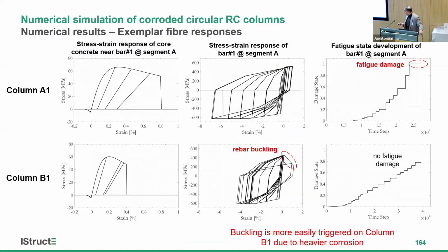And these are also some examples of the material response. So this is the confined concrete response in column A1, which was well confined. This is column B1, which is lightly confined. You see, essentially, the concrete crushing strain is around 0.4%, which is more or less like unconfined concrete. Whereas this one is much more, so we had better confinement. And this is with the buckling, and this is without the buckling, and the fatigue damage. So we could include cumulative fatigue. Essentially the power of OpenSees is we can track every single material. We can see, we can understand how things are failing at different levels.